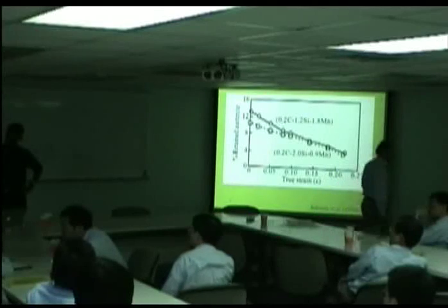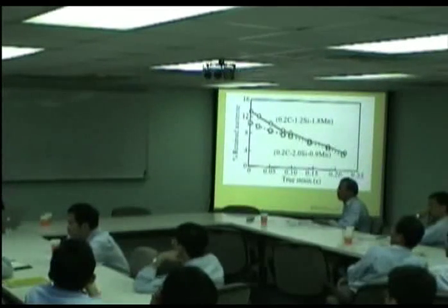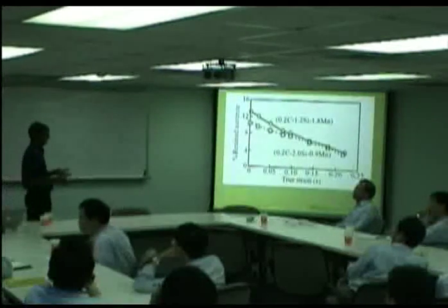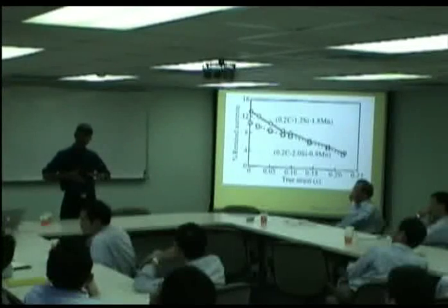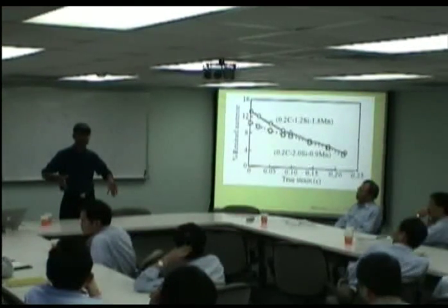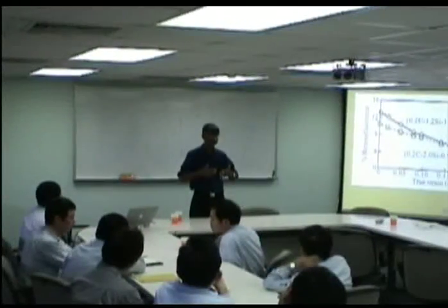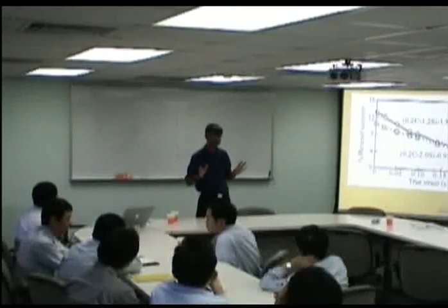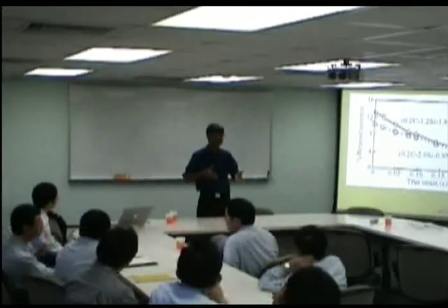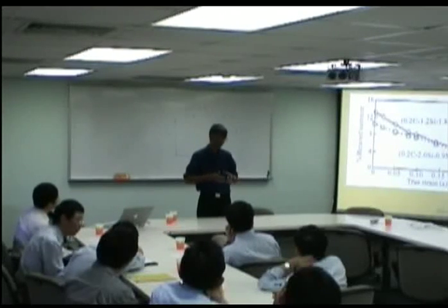Can you comment on the effect of the deformation step on the temperature? Right. So when you plastically deform the austenite, you can actually stop the martensite from forming. Because, again, you put lots of dislocations in the way of the interface, and the martensitic transformation will stop. If you put a lot of deformation into the austenite, then you mechanically stabilize the austenite.